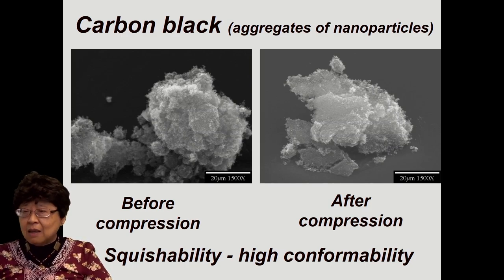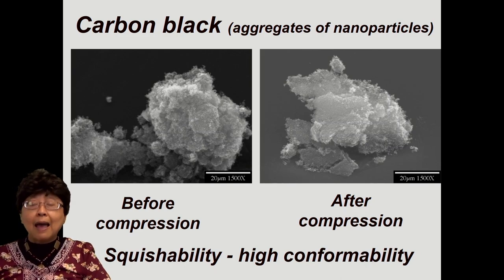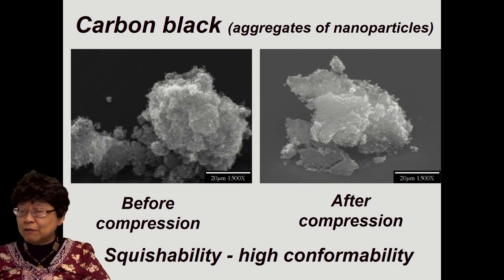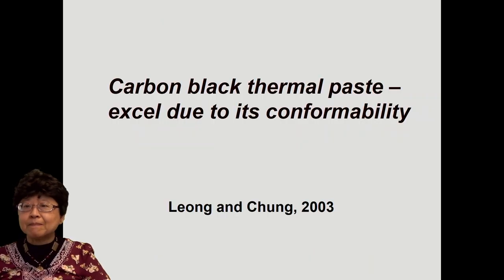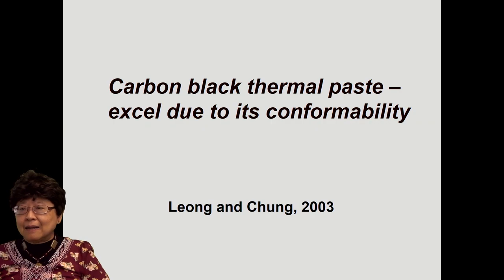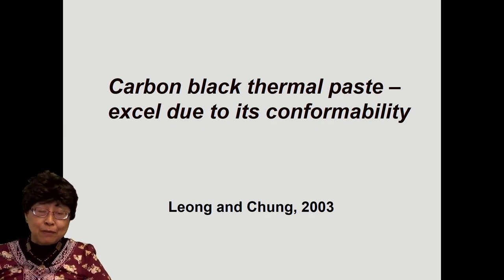with. Okay. And so the carbon black, even though it is a solid and it is thermally conductive, it is highly conformable. And by using the carbon black, I was able to invent a thermal interface material, which is very good because of its high conformability. And carbon black is very cheap also. You have a lot of that in your chimney.